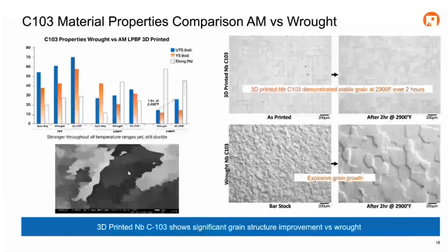And that's really related back to those hafnium carbides and oxides forming at very fine length scales during the printing process itself. So when we talk about strength, all the way out to 2,000 and 2,400 degrees Fahrenheit, we're seeing almost a double in the ultimate tensile strength, and even improvements in the yield strength, while still retaining ductility, which tells us this is a really good candidate material that's going to outperform its wrought counterpart, and we've demonstrated that now.